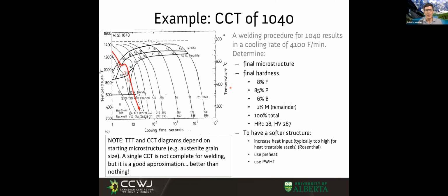That is a lot more complex because that means, all right, I'm going to suck it up that I end up with a bunch of martensite in my weld. I'm going to do a heat treatment and temper this martensite. Very different ball game, right? Now this type of heat treatment would be more of a traditional heat treatment, putting things in an oven. That said, some things are more difficult to put in an oven. If you're welding a ship, it's going to be tough to do a post-weld heat treatment there.